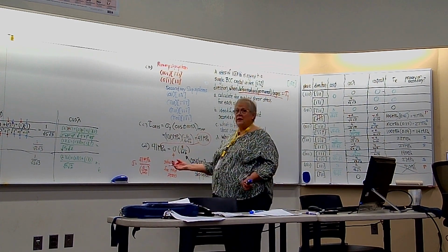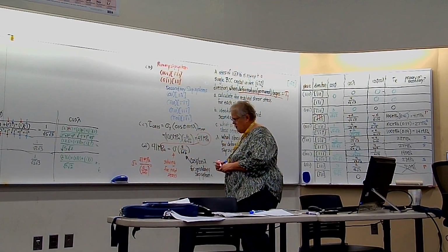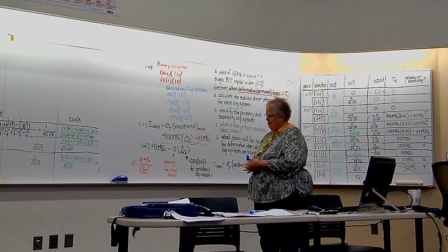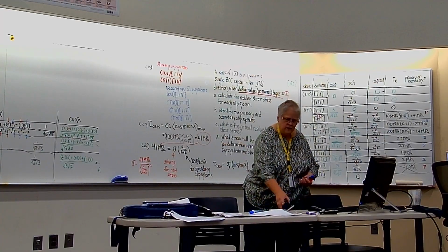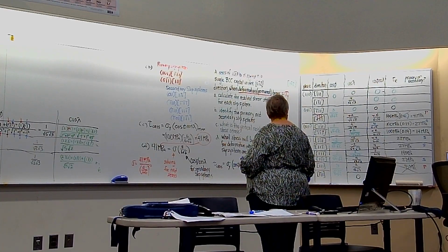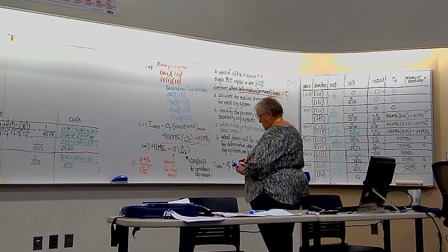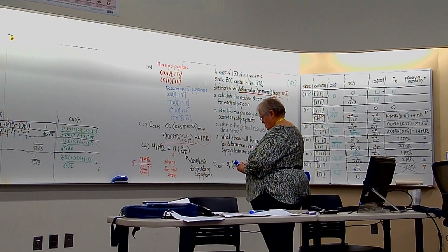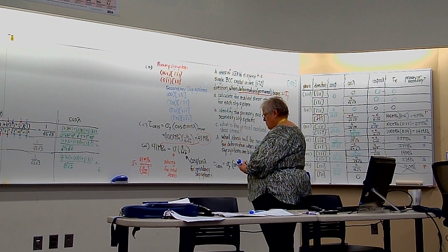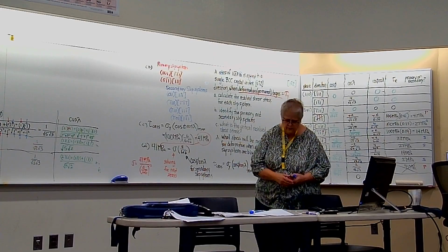And that's going to be a number bigger than 100. So I get 152 megapascals.